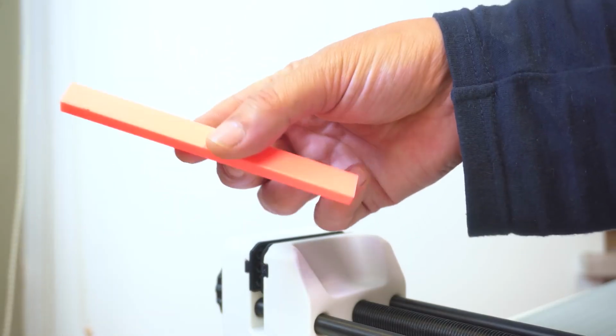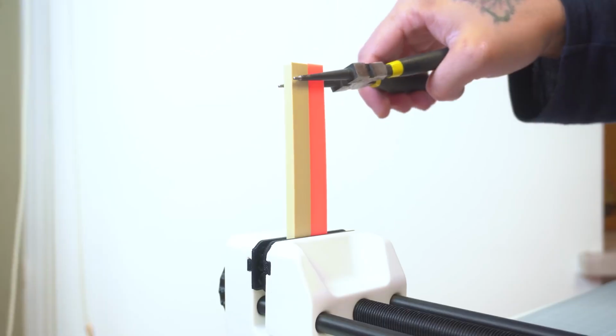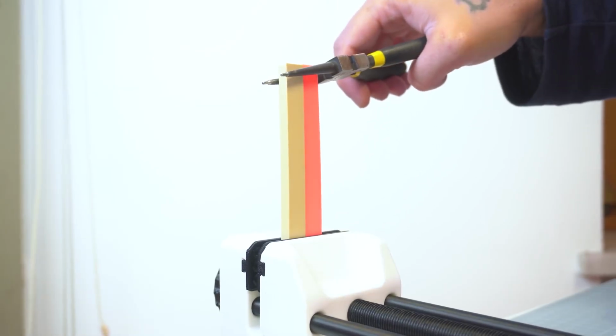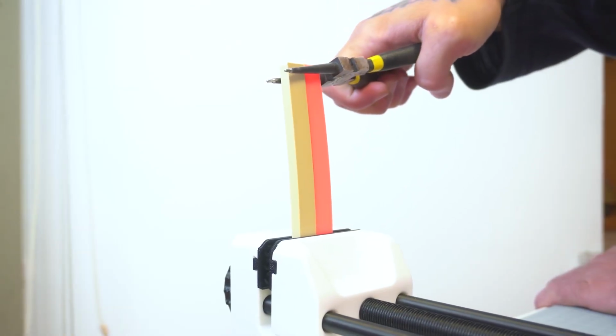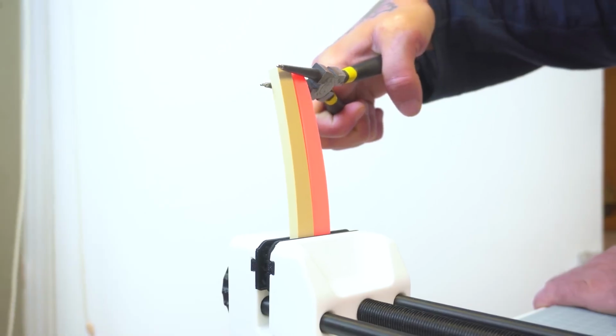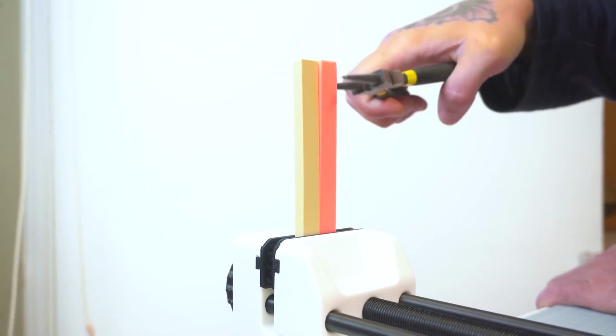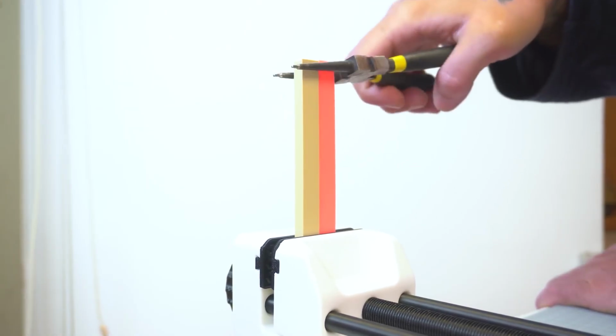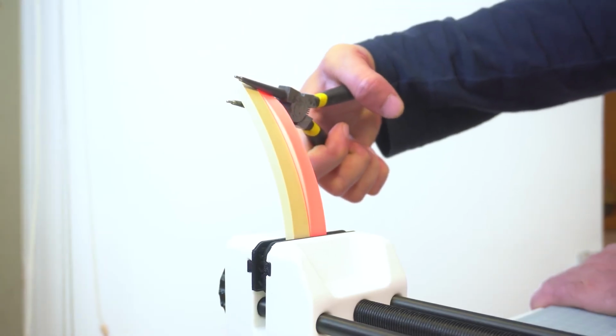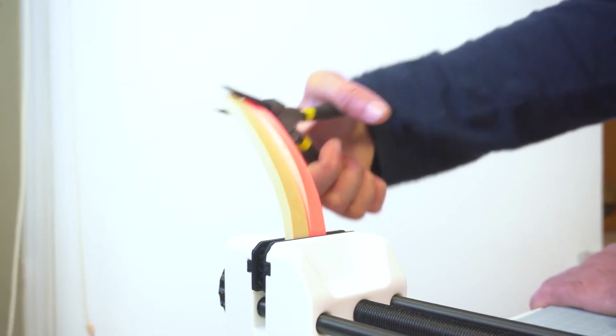And for the next test, I printed two little bars with the same settings, one of course in normal PLA and the other one in HT-PLA. And I was trying to break them and see which one was going to break first. And the crack was from the actual PLA, the orange one. In fact, it's super brittle and it cracks badly. And then bending them more and more,